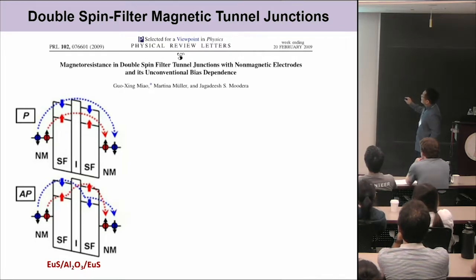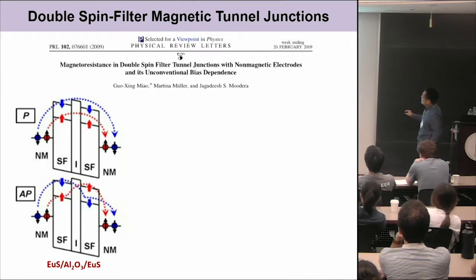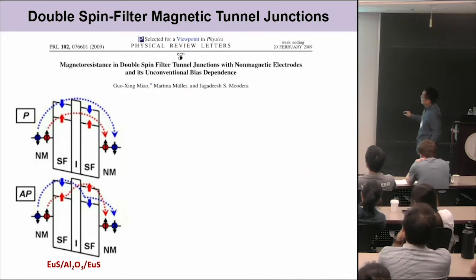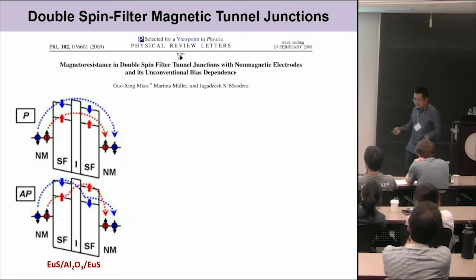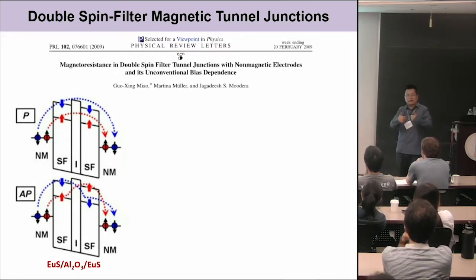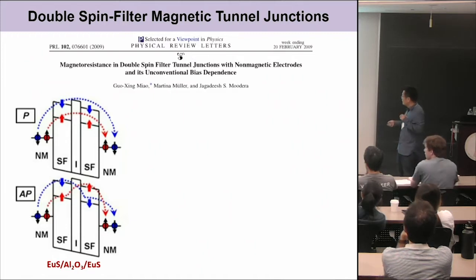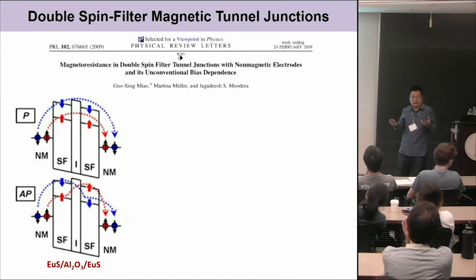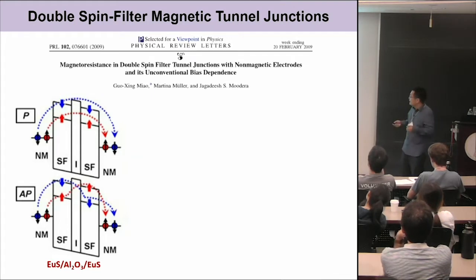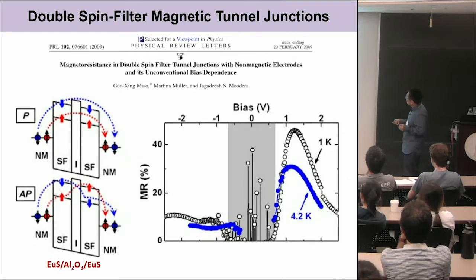About 10 years ago, the group at MIT, the Moodera group, engineered these artificial spin filters with europium sulfide, aluminum oxide, and another europium sulfide. The reason they put in aluminum oxide is, first of all, they don't want these two europium sulfide layers to talk to each other. Otherwise, you cannot distinguish the properties of the two europium sulfide layers, right? The second is that they grow different thicknesses of europium sulfide. Then they have a slightly different coercive field. Then you can treat them as different spin filters. With that, you can obtain this spin filter tunneling effect with a TMR of about 30% at low